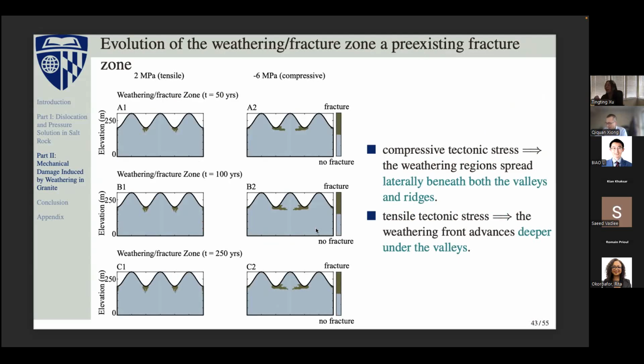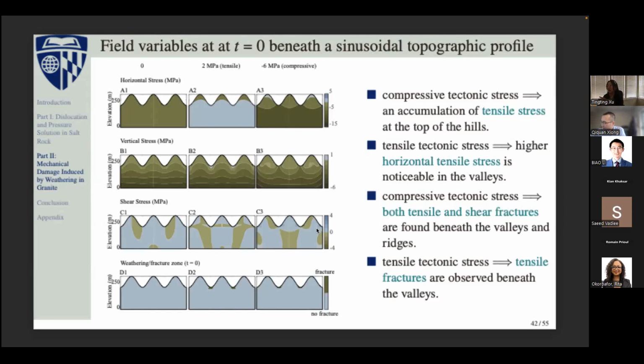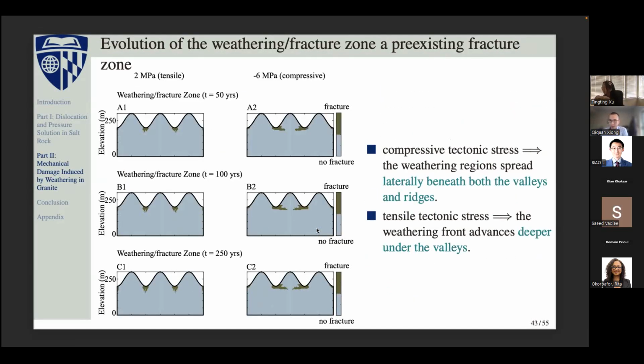And then we can see how this weathering fracture zone evolves with time. In these slides, you can see that it goes from 50 years to 100 years and to 250 years. You can see that for the compressive tectonic stress, the weathering regions tend to spread laterally beneath both the valleys and ridges. In contrast, for the tensile tectonic stress, the weathering front advanced deeper under the valleys. Those observations are consistent with observations in the field for different tectonic stresses.